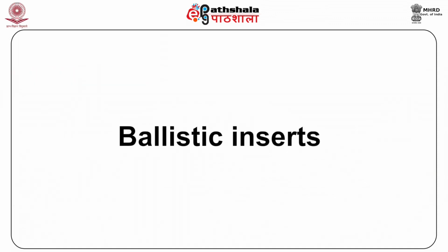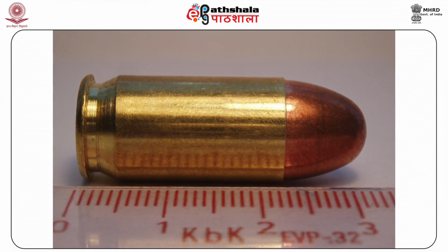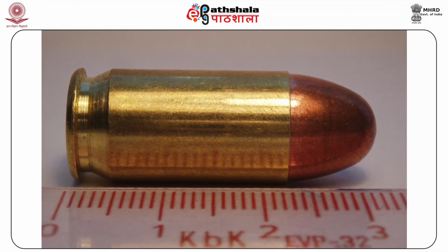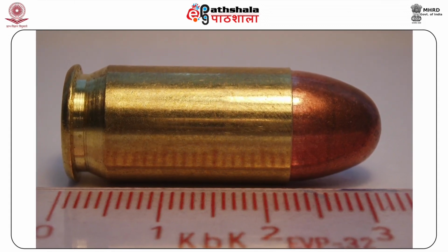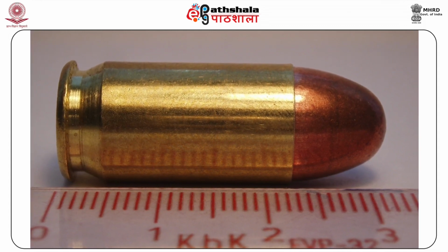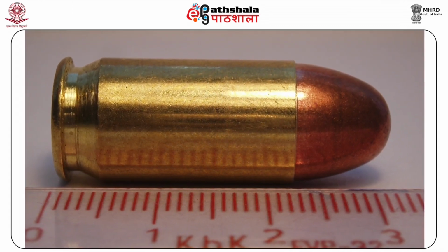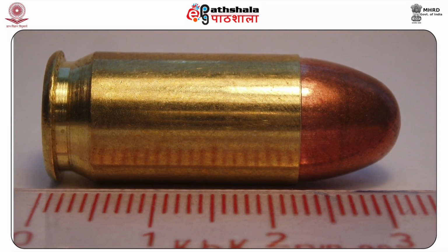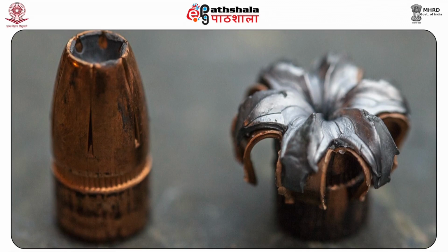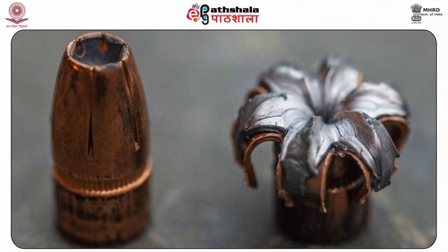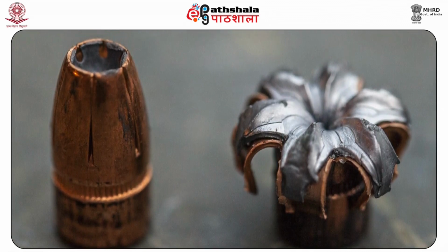Ballistic inserts. This is the name generally given to rigid plates which are placed in front of the soft body armor. Their purpose is to break up high velocity, hard jacketed, and metal penetrating missiles. Once the bullet's velocity has been reduced and its shape deformed, it will be easily stopped by the underlying Kevlar or Spectra material. These inserts are generally made from either a fused ceramic material, heat-treated aluminium, hardened steel, or more recently titanium. These can be either solid plates or small overlapping tiles.